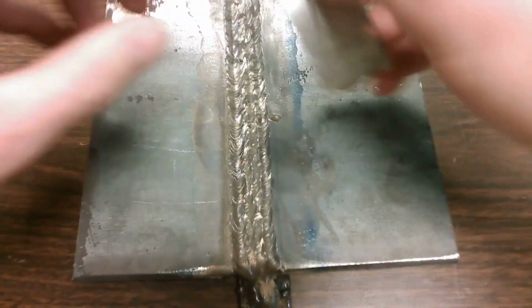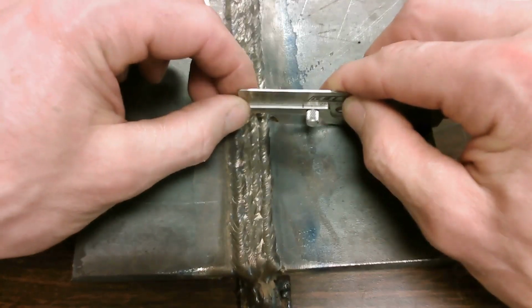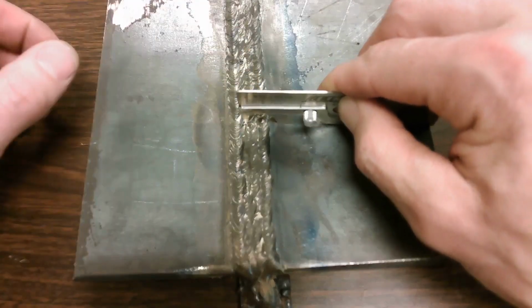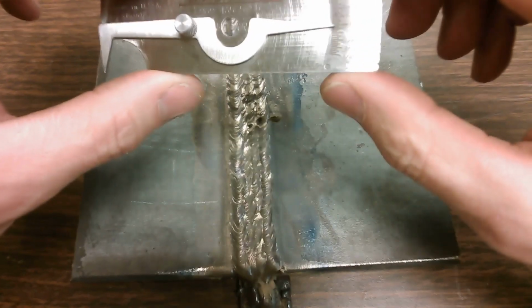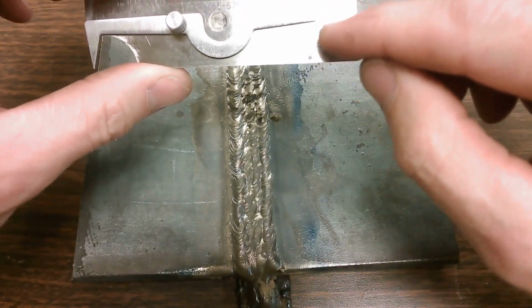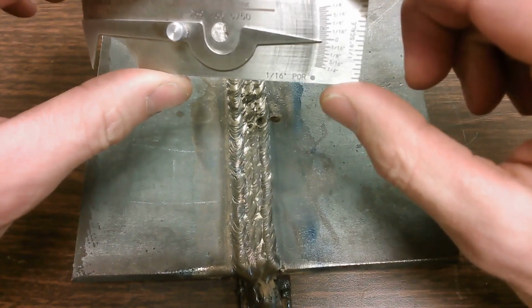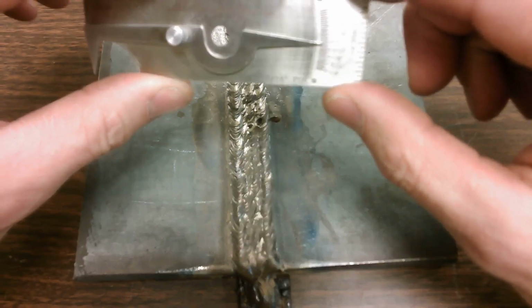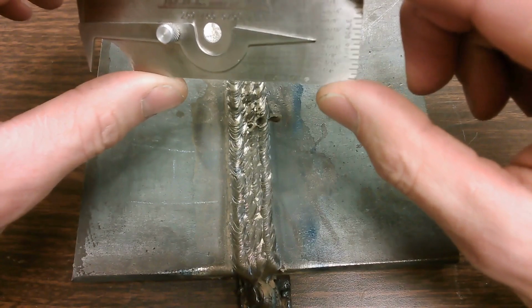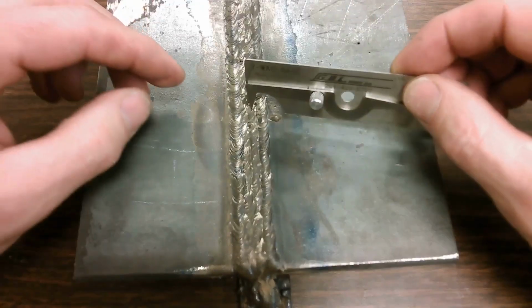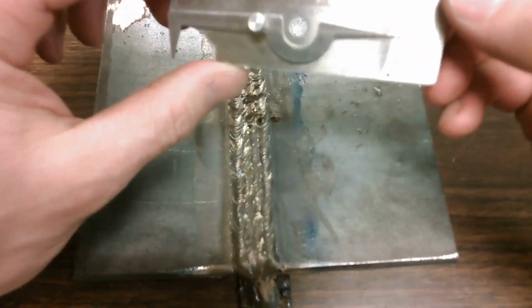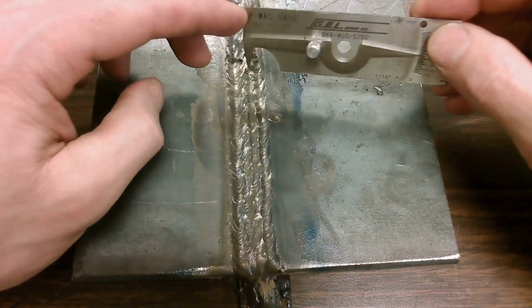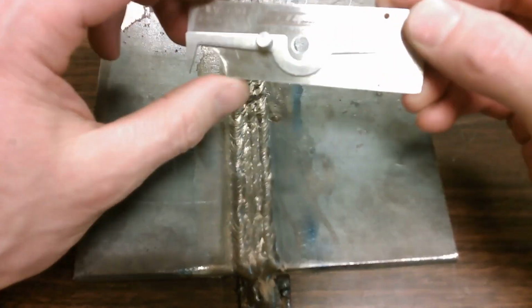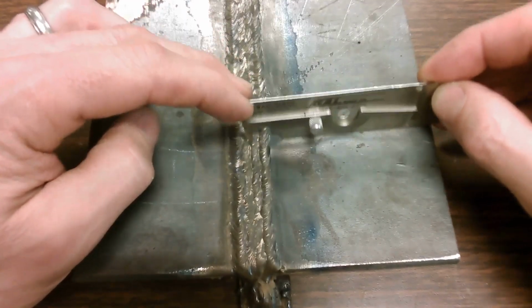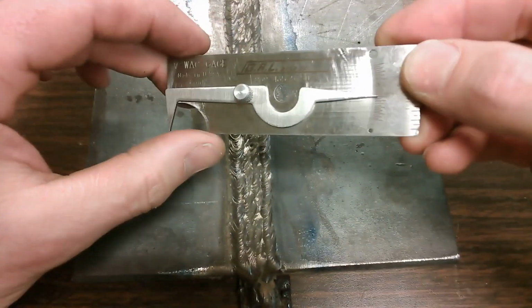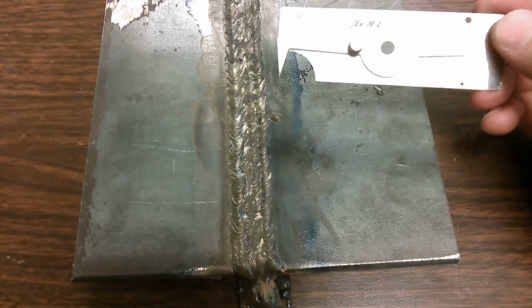So all I'm going to do is use my VWAC gauge, and I'm just going to push down into those low areas that I see and make sure that I'm still above 0. And anything down here would be above 0, so I'm definitely just barely over base metal thickness. So we're good. There's no issue with that low spot. I can check a couple other ones. Again, we're right at 0 there, so that would still be fine. And as long as we don't dip down below, we're good. So checked a few areas. Everything looks pretty good there.